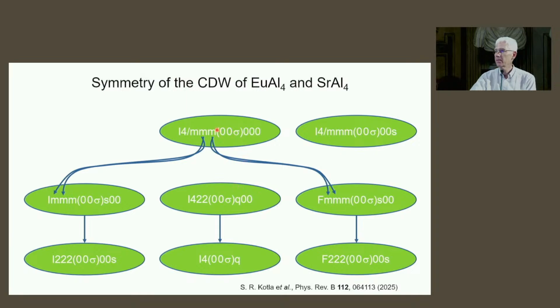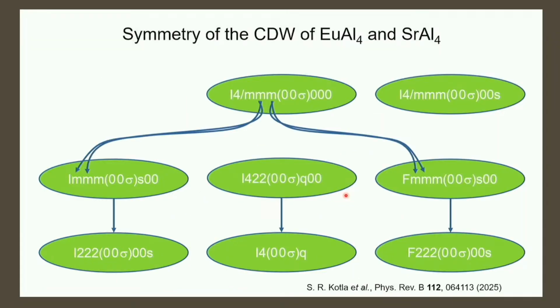And yeah, the I4/m turned out not to work well, because you can see these two mirror planes generate two different mirror planes which have a different symbol here. One is mirror s, and the other is mirror 0. Here the two mirrors are the same by fourfold rotation, so they are both s or both 0. And that turned out not to give a good structure. The s is the intrinsic translational component along the fourfold axis. Don't need to know in detail, just that 0, s and q are different. s is for 1/2, q is for 1/4. And then we can take subgroups of these groups and we get the non-centrosymmetric I222 or F222.